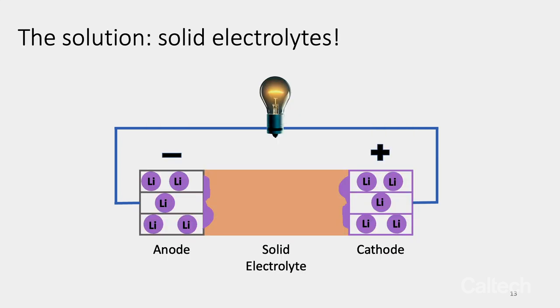So how exactly can we go about overcoming this principal problem? As I told you, the electrolyte generally consists of organic liquid molecules or materials that can combust when given enough heat. One way to circumvent this is to actually replace that liquid material with a fully solid electrolyte material that's more chemically stable and won't allow for the formations of those dendrites by essentially pressing down on them or inhibiting their growth. There are a number of people working on this problem. The nice thing about these solid electrolytes is that they're not as vulnerable to this shorting problem or to external abuse, which can also cause these kinds of explosions.